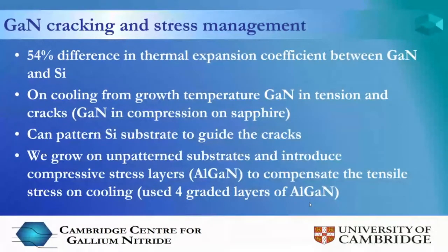And in fact, to achieve unstressed, uncracked gallium nitride, we put in 4 of these layers, and each one was graded. So we actually grew aluminium gallium nitride as a graded composition of gradually increasing aluminium content. And we got totally uncracked layers. So this was how that problem was solved.